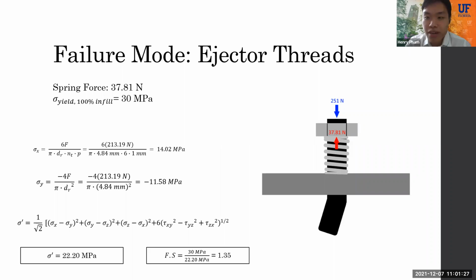So for our ejection mechanism, we did a failure analysis on the ejector threads to ensure that threads do not break off during the ejection process. By using the maximum force produced by the downward motion of the drive nut and the force from the spring, we were able to find the forces that were acting on the hex nut. From there, we were able to calculate the bending stresses and axial stresses located at the 3D printed threads. Combining these stresses, we found the von Mises stress that was located at the threads, and we found that the maximum stress that the threads experienced was 22.20 megapascals.